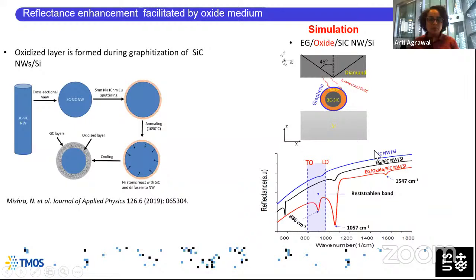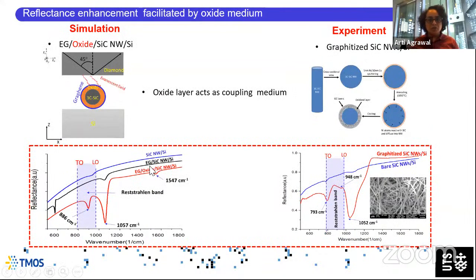So once again, to recap, bare silicon carbide nanowire is the blue curve. If you graphitize it, the behavior between the blue and black curves is not very different. You need to include the impact of the oxide layer to be able to sufficiently capture the behavior of this graphitized nanowire. And then this looks quite similar to that of the actual experimental results. This is just showing you the comparison. As you can see, the experimental and the simulation results look quite similar.